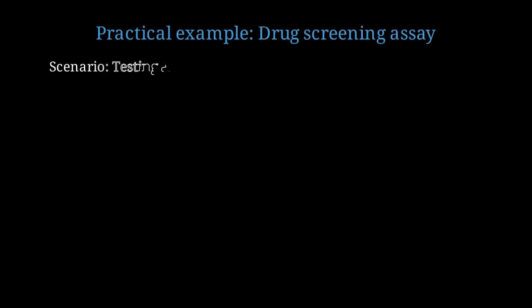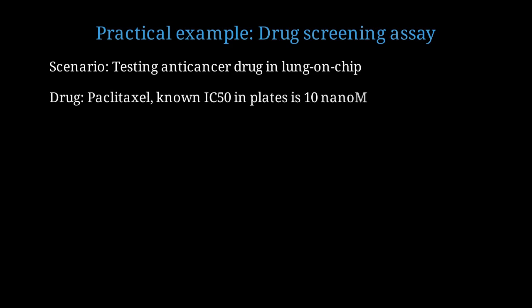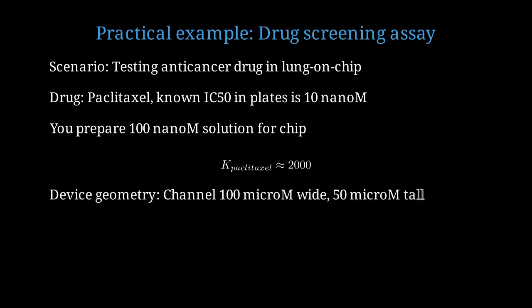Let me walk through a practical example of how this affects a drug screening assay. Imagine you are testing an anti-cancer drug in a lung on a chip device made of PDMS. The drug is paclitaxel. The known IC50 in standard culture plates is 10 nanomolar. You prepare a 100 nanomolar solution for your chip experiment, expecting a strong response. But paclitaxel has a partition coefficient of approximately 2000. Your device has a channel 100 micrometers wide and 50 micrometers tall. The volume ratio is approximately 20.